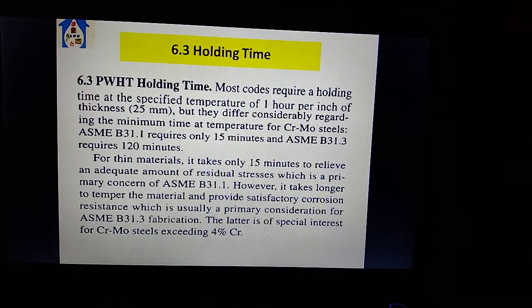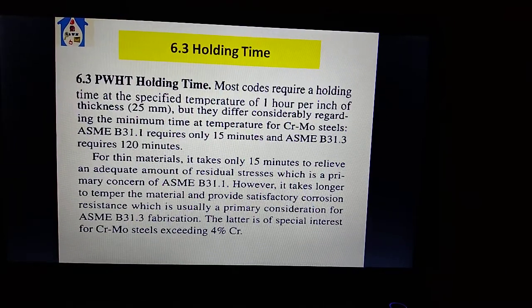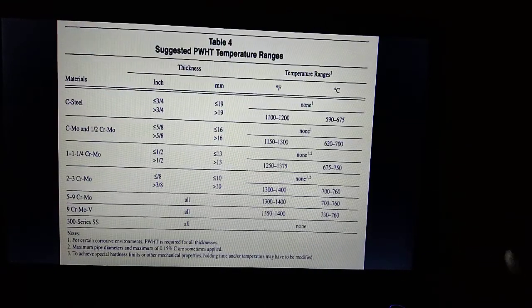For 15 minutes to relieve an adequate amount of residual stress, which is the primary concern of ASME B31.1. However, it takes longer to temper the material and provide satisfactory corrosion resistance, which is usually a primary consideration for ASME B31.3 fabrication. The latter is of special interest for chromium molybdenum steel exceeding 4% chromium. Suggested PWHT temperature range is shown here.